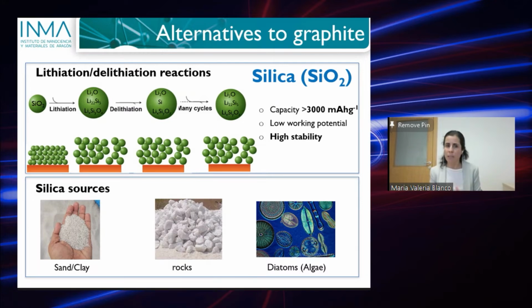So why does silica have this nice stability? There are not many experimental results on this, but there are some theoretical calculations in which it is thought that silica reacts with lithium as an in situ convertible oxide, which means that silica will create silicon upon lithiation plus other components, for example lithium silicate, lithium disilicate, lithium oxide, and so on. The produced silicon will further react with lithium with a known reaction, and all the rest of the phases, the silicon oxides and the lithium oxide, will serve as buffer phases to the silicon expansion and shrinkage. So at the end, we will have some silicon that will be lithiated and delithiated, but in a matrix of non-active species. This will confer to the silica anode high stability, but also high capacity.